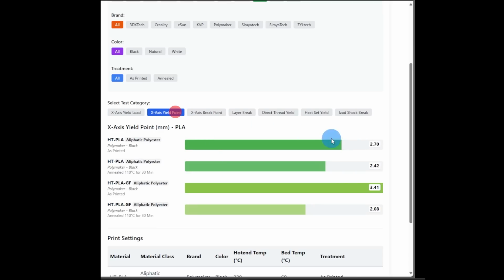It's interesting. As far as how far it stretched before it breaks, well, the High Temp PLA glass fiber unannealed stretched a lot further than the others, but it held on more. And then the break points coincide right along with the stretch points or the yield points. Layer adhesion, nothing really good, nothing really bad, but layer adhesion did go down on both of them when annealed.